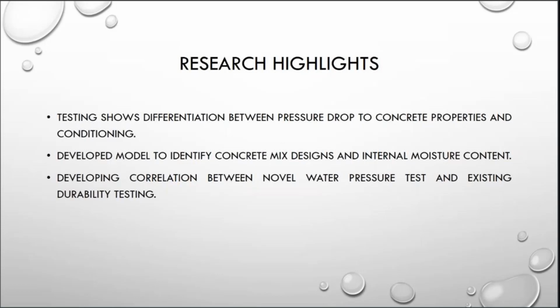Any other comments? I think for the most part, for field cases, I agree. Yeah, you can roughen the surface to remove that skin to resolve some of the issues of carbonation, and the moisture content we feel can be controlled as well. Yes, the other thing is that the surface needs to be fairly smooth because of the gasket. We need to seal it, so it would have to be ground down to a fairly level surface so that we can get a good seal between the system and the concrete.